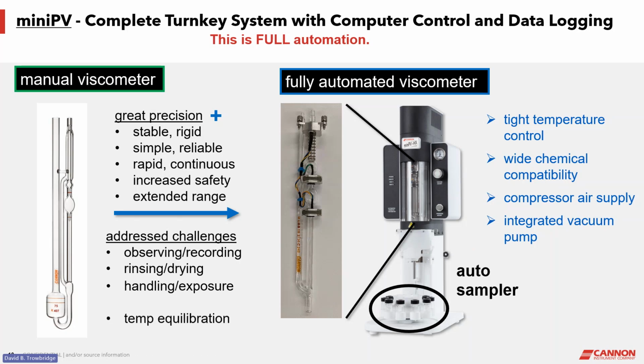Then we have also the fact that the temperature equilibration occurs more quickly. This is because the sample is loaded through the capillary. The surface area here for transferring the temperature into the sample is much greater than the surface area that's experienced when you're trying to heat up the sample in this large reservoir of the manual viscometer. So we pick up an advantage in the equilibration time as well.